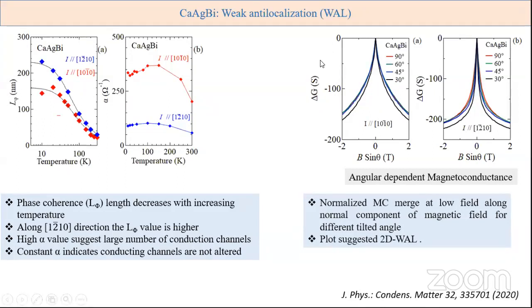To look at the origin of this weak anti-localization property in the magnetoconductance, we measured magnetoconductance at different tilted angles. Theta here is defined as the angle between current and magnetic field. At different angles, the magnetoconductance almost merges at low field, but it deviates at high field. That means it has more of a 2D conduction channel effect rather than a bulk contribution. The normal component of the magnetic field is merging at low magnetic field, also observed in other topological semimetals like Bi2Se3 and others.